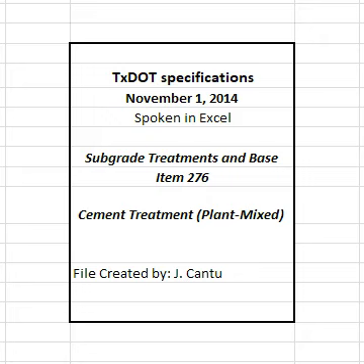Construct individual layers to the thickness shown on the plans. Maintain the shape of the course by blading. Correct or replace segregated areas as directed, at no additional expense to the department. Construct vertical joints between new cement-treated base and cement-treated base that has been in place 4 hours or longer.